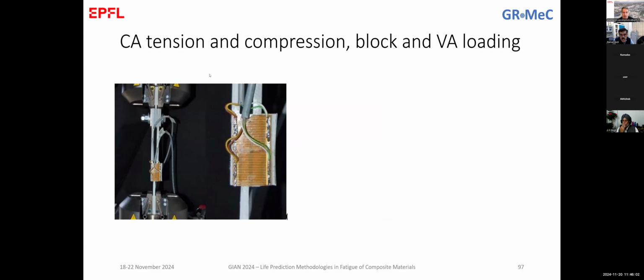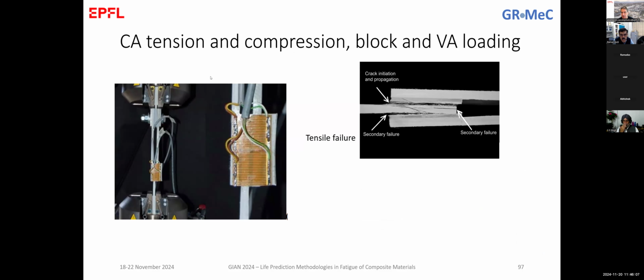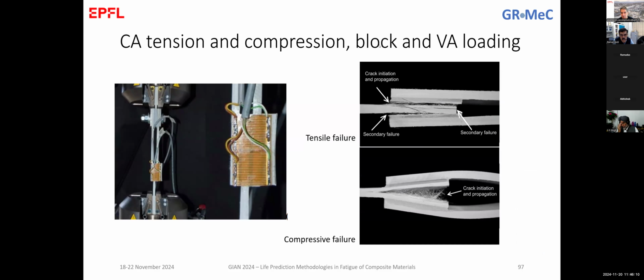Okay. So the fatigue testing continued with block loading and variable amplitude loading. And we had also the block loading, where we applied tensile loading and compressive loading. And what is very, very interesting here is to see that in tensile loading, we had the typical failure of cracks propagating along the bond line in both sides. This was a secondary failure after the failure of the main, the basic failure here. We had this secondary failure.